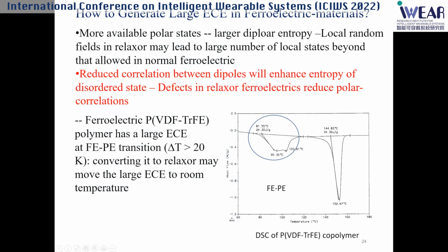And if you convert this into the adiabatic temperature change, this means even at this transition you can get a 20 Kelvin temperature change, electrocaloric. But this would be at high temperature.